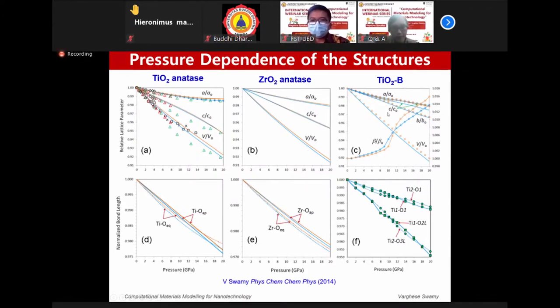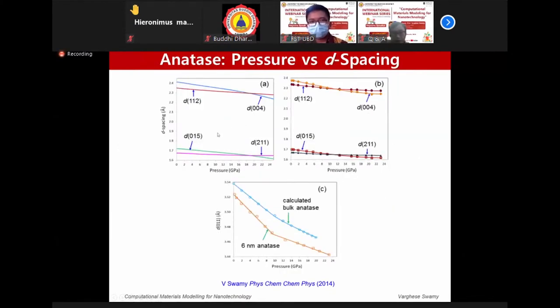Now, coming over to the titanium oxide bronze structure, you can see that there is some structural destabilization happening around 12 GPa, where the nanoparticles are known to become disordered. And you can also see similar crossing of the evolution of the TiO bond lengths. So then I further calculated the d-spacing for different planes, and you can see that there are crossings happening around 14 to 18 GPa. When you look at the experimental data, you've captured it earlier, around 10 to 12 GPa, where the disordering or the lattice stiffening is happening.